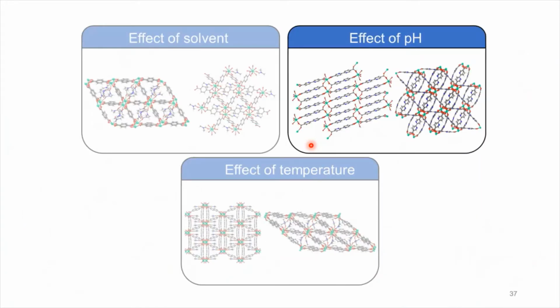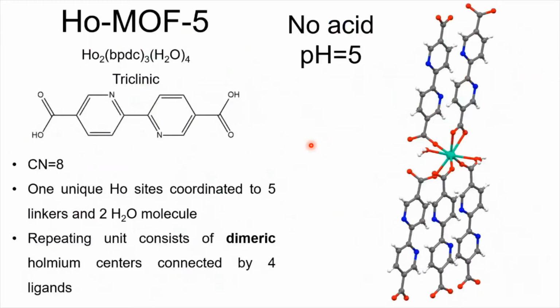Now, what happens if we concentrate on different pHs? And now we switch, instead of terephthalic acid, we'll use one of the derivatives, a bipyridine-based linker. And we were very interested in this because it has those nitrogens in the rings, which will maybe allow us to bind something in there. So if we go back to the intro, we want radiosensitizers. So maybe this group will allow us complexation with platinum or nitric oxide.